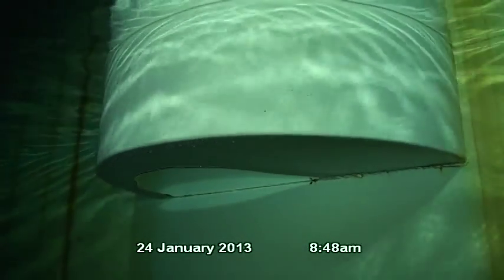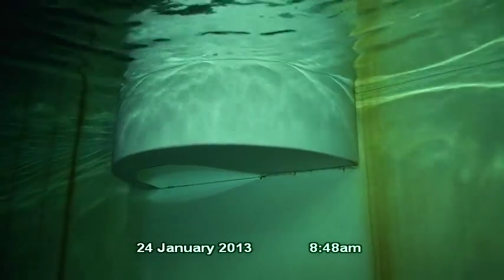A portion of the overflow weir box is located below the water line. The overflow weir box is coated with epoxy, and coating defects have resulted in light surface corrosion in a few areas on the overflow weir box. It does appear to be securely welded to the shell. Additional areas of pinhole type corrosion are present in a couple of areas on the welds. The shell is stained around the overflow weir box. The center pole is the only support column located on the interior of Marshall Reservoir. The epoxy coating is heavily stained near the waterline.